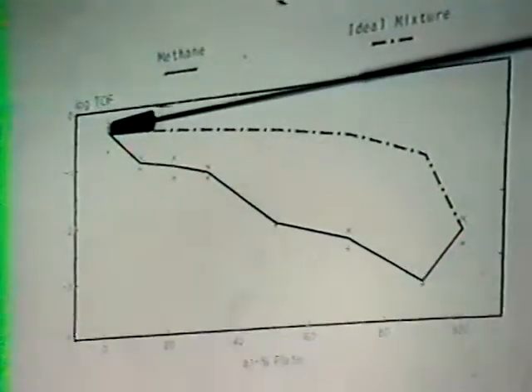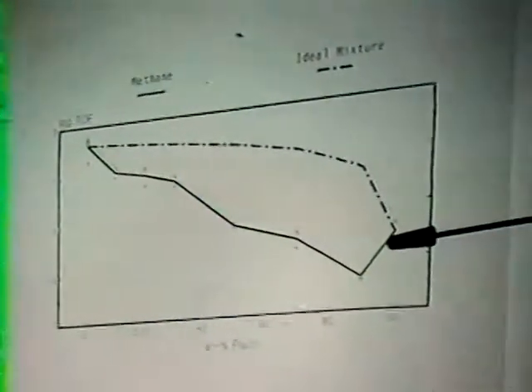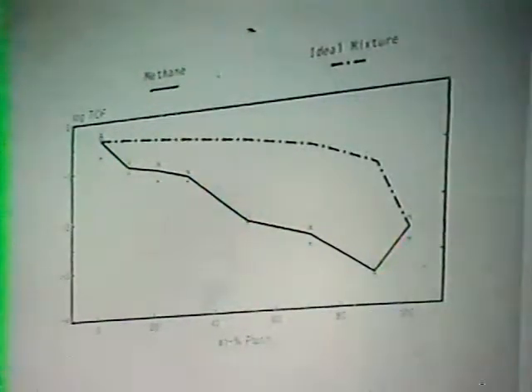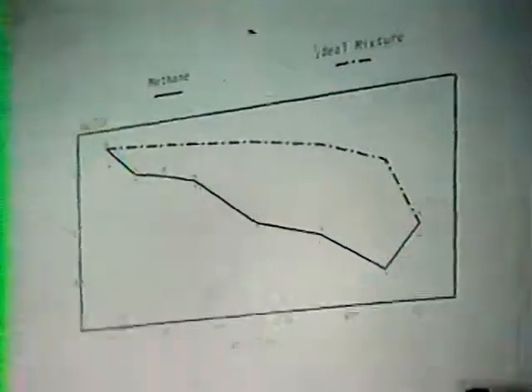If we look at the surface of this catalyst by dehydrogenation, we get a tremendous fall off in turnover frequency as we go from the pure nickel system towards the pure platinum system, as you'd expect. This would be maybe what you'd expect if you had an ideal mixture, that is, the surface being the percent nickel that you would expect from the bulk. If you then use this to come up with some quasi-determination of surface composition, it would suggest that as you increase the amount of platinum in the system, there is a very quick enrichment of the surface in platinum, which certainly fits what one sees with the single crystal studies of the bimetallic phases.